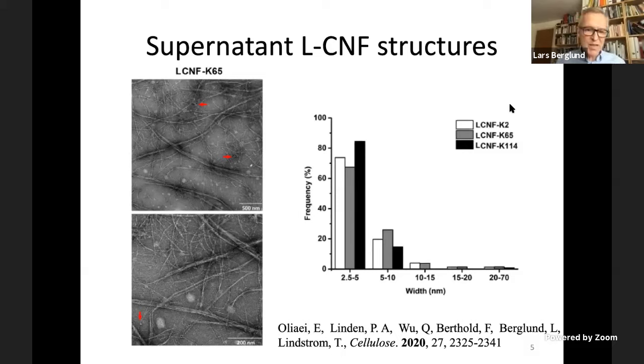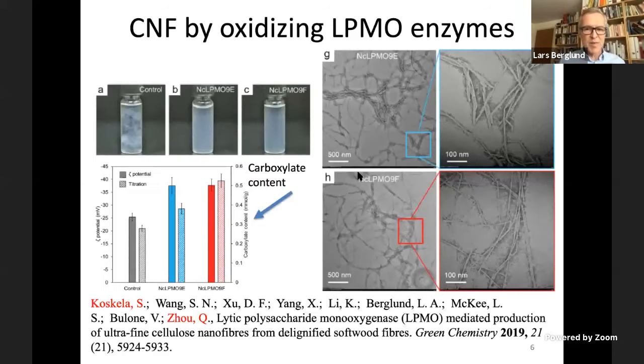If you take the supernatant and then you look at the fibrils in TEM, you can see here we have a 500 nanometer scale bar here. So you can see some of the fibrils are actually of very fine diameter, although some of them are larger. So we can see that perhaps the largest are 70 nanometers or something like that. But if you look at the distribution here, you see there's a large fraction of the fibrils that are actually fairly small. So that's an interesting possibility.